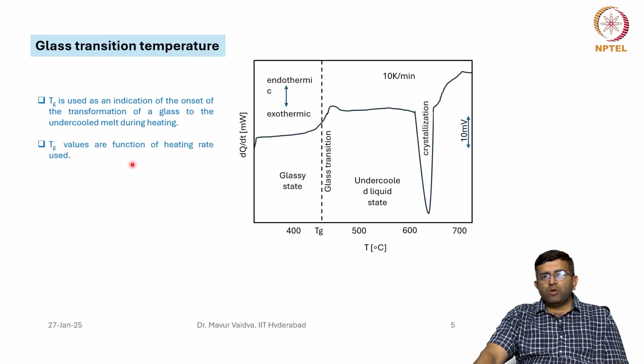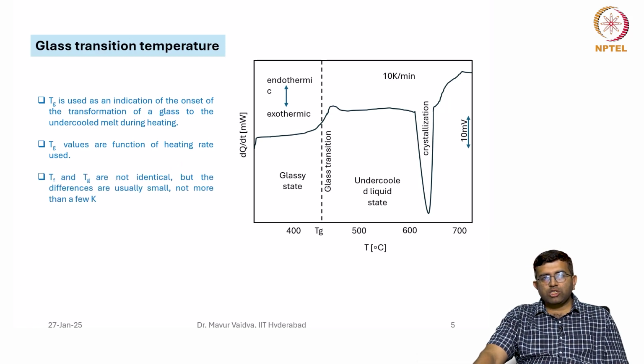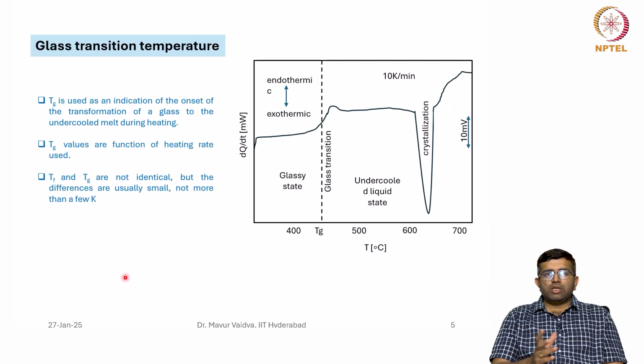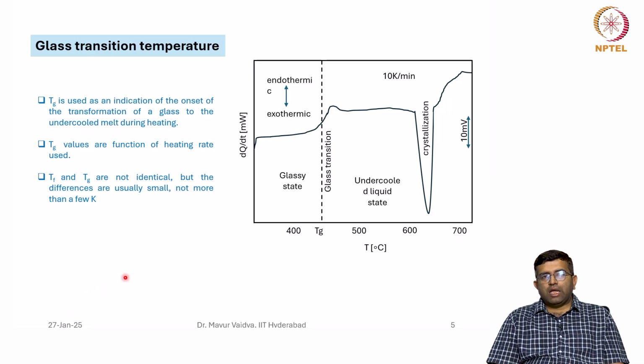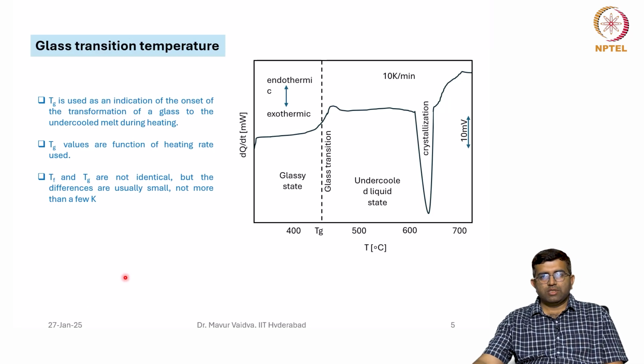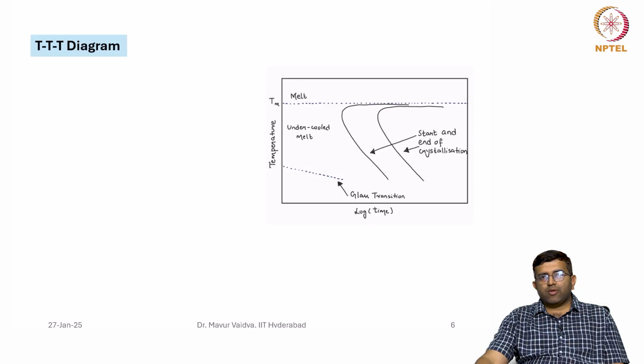Again, the TG values are also a function of the heating rate used. Depending on the heating rate, you may observe a different TG. Although TG and TF are not really identical, the differences are not more than a few kelvins. Let us also see the TTT diagram, that is, the time temperature transformation diagram for glass.